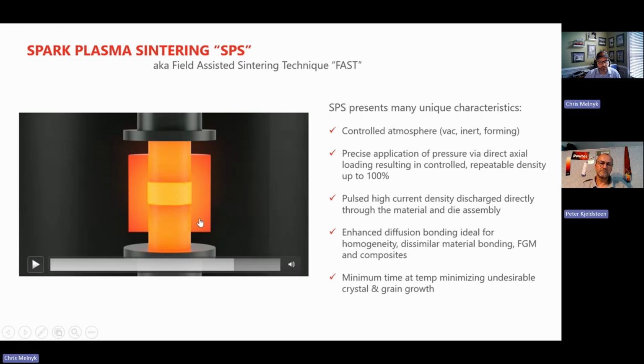And so if you compared this with, say, hot pressing, where you have heating elements way out here and it was separated with a vacuum, that's not exactly an ideal way to get heat to transfer into your die set. So you'd have a heating element with a maximum temperature. Then you have a gradient, and that's radiating, and then that heat has to be absorbed on the outside of the die and make its way into the inside of the die. And so those processes typically take like 12 hours, depending on the material. It could be into the days sometimes.